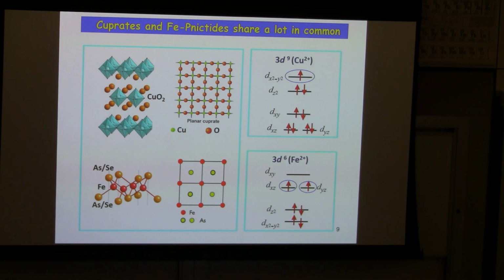Okay, as a consequence of that, other than that special filling, there are many commonalities between iron-based and cuprate. Both systems basically show a square lattice structure, and the 3d transition metals copper and iron are strongly bonded with the neighboring anions: oxygen in the case of cuprate, and arsenic or selenium in the case of iron-based ones. This is the structural commonality, but I would like to stress that the very strong covalent bonding between anion and cation is another important commonality.